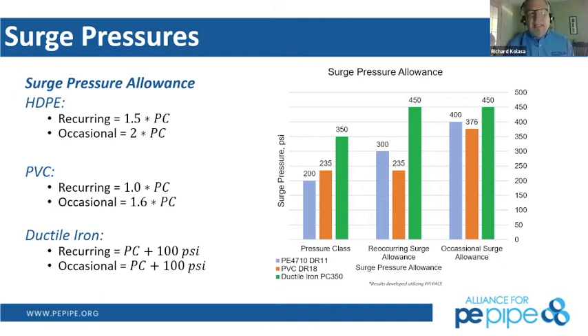But the interesting thing about reoccurring and occasional design, if you can design it either way and how you want to do it, we don't really have a negative effect with these surge events because it's actually a multiplier of 1.5 and 2 on the pressure class. We actually have higher pressures that we can handle even if you have these bad surge events that occur, and you'll be protected for the lifetime of that product based on these operating pressures that you see on this graph. So we're protected, and you can be reassured that you're not going to have failure.